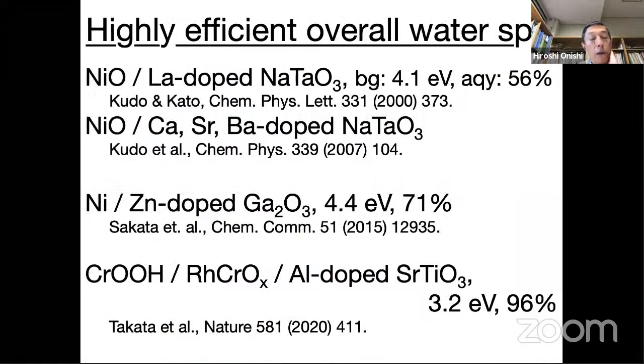After that, many photocatalytic materials were found in a similar sense. The first column shows the first one, sodium tantalate. This is the main material of the semiconductor, and they put in a small amount of lanthanum cations. So in this area, we recognize the lanthanum doping to sodium tantalate. And then they get a quantum yield around 50%.